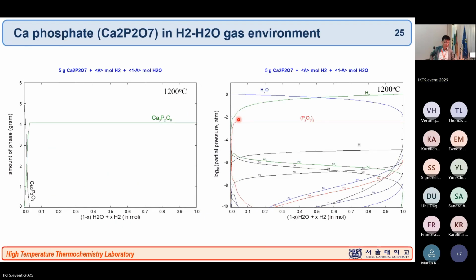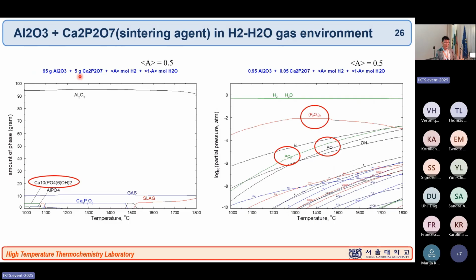That's possible. And now this is calcium phosphate. Calcium phosphate is sometimes used as a bonding material in some refractories. If you put this one in H2O condition, it also has a problem. Calcium phosphate, P2O5, is not a very stable phase. If you put this one in the H2 condition, it can evaporate P2O3 gas phases. So you can see a lot of P2O3 gas phase formation here, even at 1200 degrees Celsius. And now if you put this one with alumina, with that bonding material, in the H2-H2O condition, about 50-50, you can see that at around 1000 degrees Celsius you can start to see some calcium phosphate hydroxide formation as well.